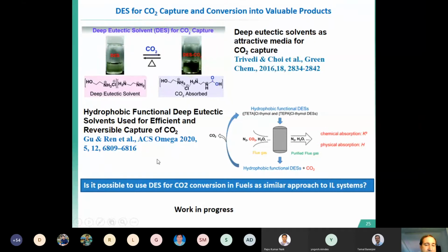Another article, more recent, in 2020, this year, from Ren and co-workers, proved that hydrophobic functional deep eutectic solvents can be used for efficient and reversible capture of CO2. Here, they are using a hydrophobic functional deep eutectic solvent and CO2 for the purification of flue gas by chemical and physical absorption. And it is clear that it's possible to use deep eutectic solvents for CO2 capture and sequestration.